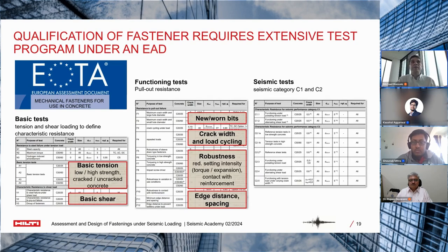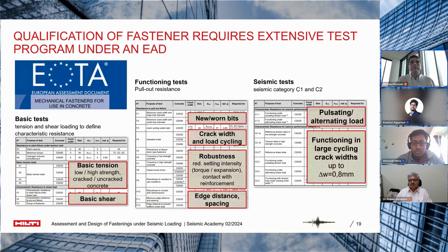And newer is the seismic qualification tests. And this is what we need to do as well for anchors that we qualify for use under seismic conditions in Europe. And there, the loading on those anchors is not anymore static or continuously increasing. So there we also test the anchors under pulsating alternating load cycles and also crack cycles up to a crack width of 0.8 millimeters.